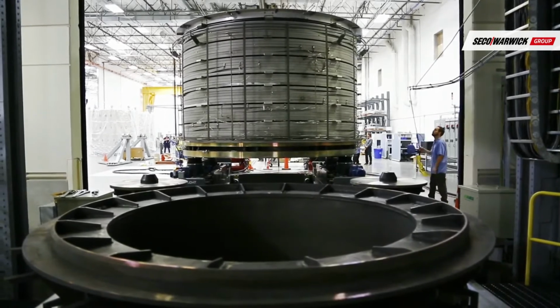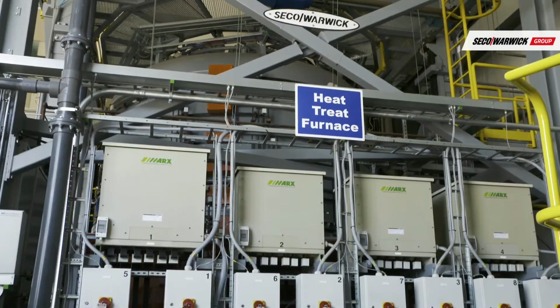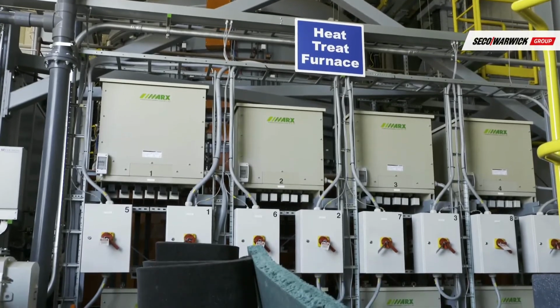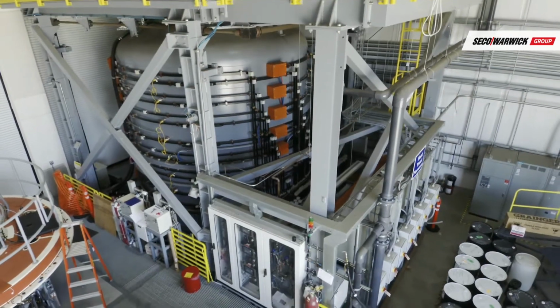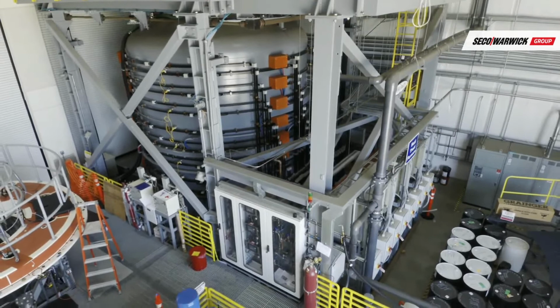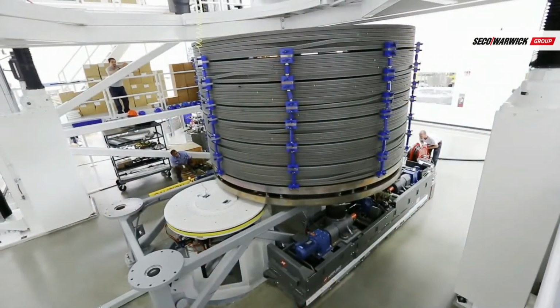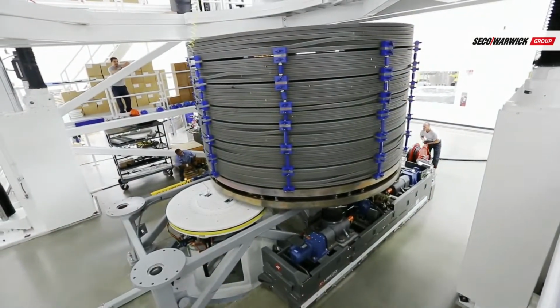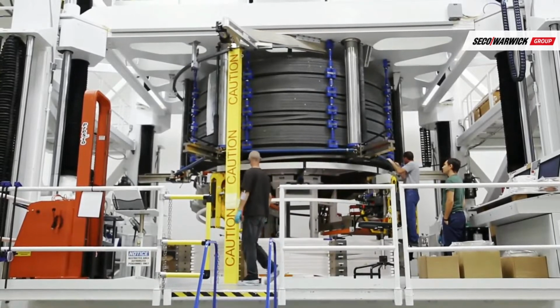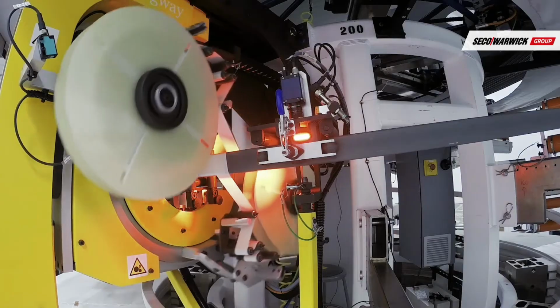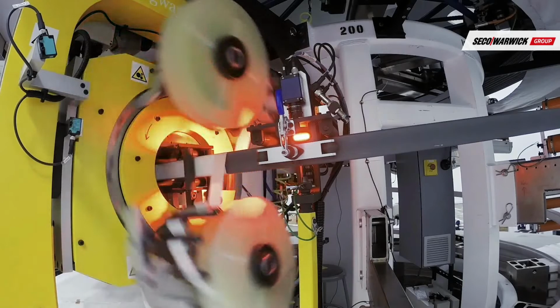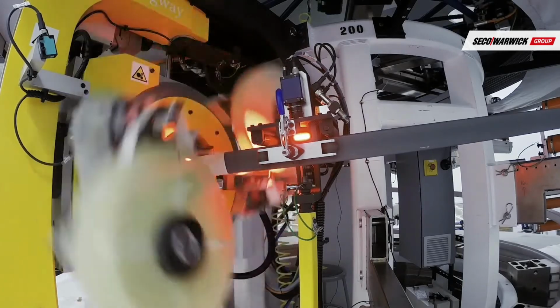During the heat treatment, the module is heated at temperatures over 1,000 degrees Fahrenheit for more than 14 days, after which it is slowly cooled for a week to complete the process. To keep the electrical current in the conductor, every inch of the steel-jacketed superconductor must be wrapped with 6 layers of electrically insulating tape, a total of 180 miles per module.